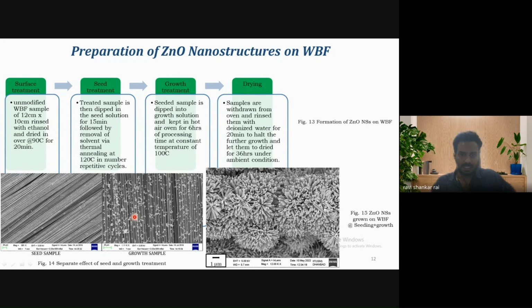So these are three FESEM images. The first one is just a seed sample, treated only with the seed treatment. The second sample has been treated with only the growth treatment. But the third sample has been treated with seeding followed by growth treatment, so that you can clearly see there is a uniform growth of the nanostructure, and the size of the nanostructures and nanorods is completely favorable. So we need to follow seeding followed by the growth treatment.